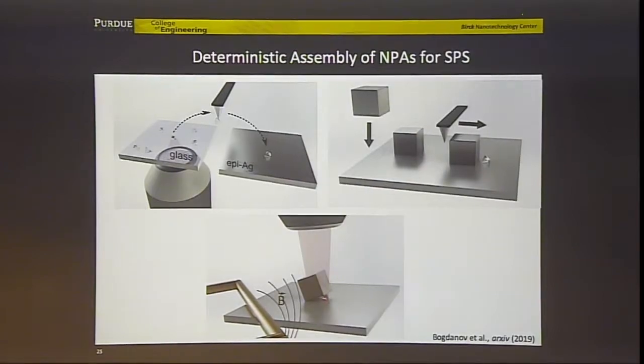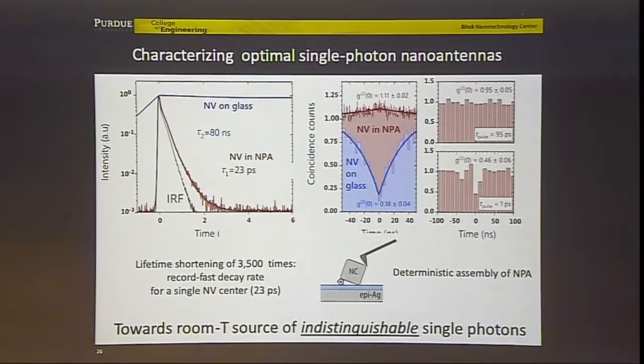What we are doing now is precise deterministic assembling of these antennas. Basically, we pre-select efficient single photon emitters based on nitrogen vacancy in nanodiamond or some other. I will talk about this later. You pick up this nanodiamond with the tip of an AFM, place it on epitaxial silver, then you push a cube of silver, which works as the outcoupling antenna, so that it climbs on top of this single photon emitter. And by the way, nitrogen vacancy also has a very good spin degree of freedom, which could be used as quantum memory. It has a very good long coherence time, which you could excite with microwave radiation and detect optically.